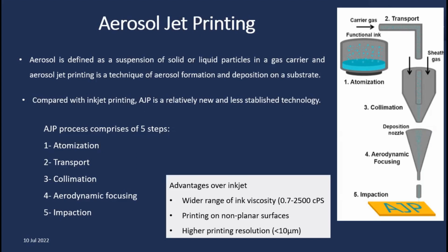Then it is further pointed in a precise direction using another system so that it passes through a very fine nozzle and then impacts your surface. So you see, basically it's nothing but a cloud of nanoparticles in a droplet formation, which is being carried from the tank all the way to your printhead. And when you do that, you can play with a range of viscosities because anything that can be made into an aerosol can be worked with these techniques, which is not possible with inkjet printing. And because of this distance that you can vary between the printhead and the substrate, you can now have 3D surfaces here.